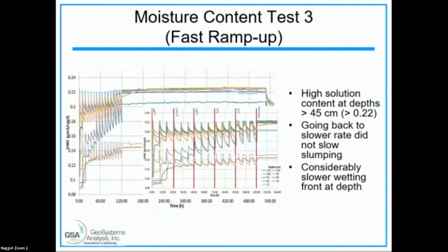And then for the fast ramp up, here we saw this up and down in the water content, but we were basically up in 120 hours, so basically around 5 days, we were at the full irrigation rate, and we saw fairly high water contents, but actually the lowest water contents were at the near surface, 15 and 30 centimeters, so kind of surprising. And again, lower wetting front at depth.